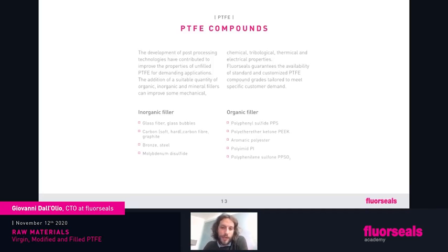This is not really helping the selection of the fillers, because the golden rule for PTFE compounds is that what we are going to add to our PTFE matrix as a filler has to withstand the sintering temperature of PTFE. Sintering temperature of PTFE is above 350 degrees. This means only a few materials, mainly organic, can withstand the temperature. On inorganic, it's easier to select the right filler. But just to give you an example, why is there no PTFE plus polyamide, plus nylon out there? Nylon is one of the widest, most used plastics in the world.